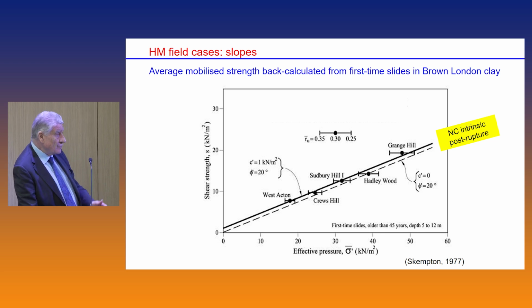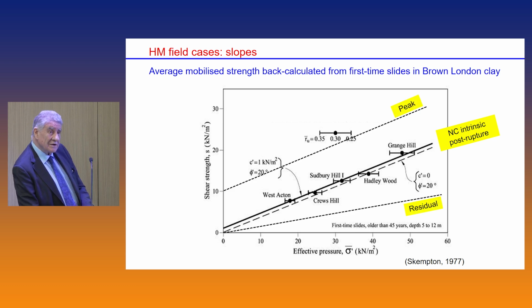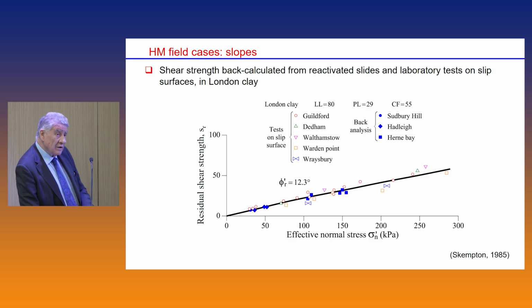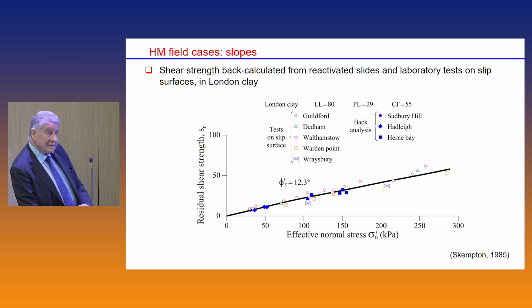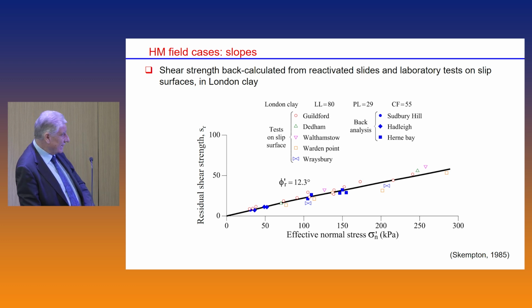The puzzle was also compounded by the fact that when you back calculated the strength explaining the failure in a number of places, you could get a failure envelope, which turned out to be very close to the intrinsic strength, or the strength of the reconstituted material, which we know now is similar to that of the post-rupture. Very different from the peak, very different from the residual, somewhere in the middle. Also, interestingly, when the back analysis was performed on reactivated landslides, they found that the residual strength was operational there, around 12 degrees in the case of London clay, which means that once you got to residual, there is no way that the former strength can be recovered. That's not strange, because it's difficult to envisage how this oriented fabric could actually be rearranged into a different pattern. So that was quite clear, but the first time slides were creating a puzzle.